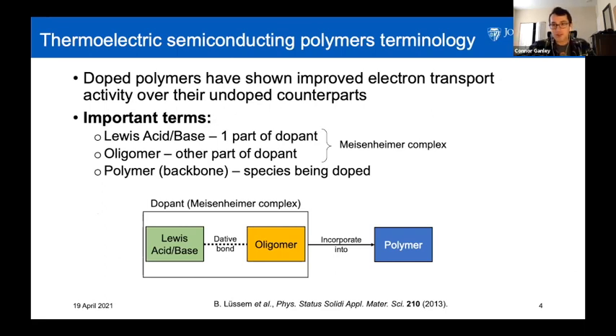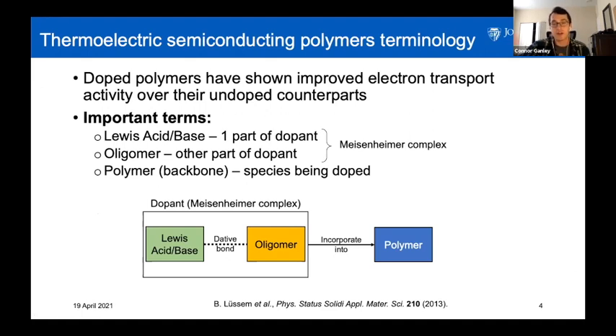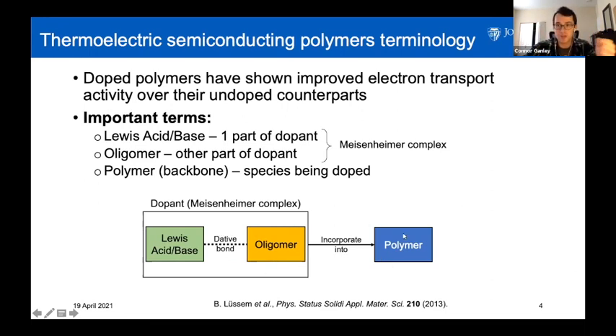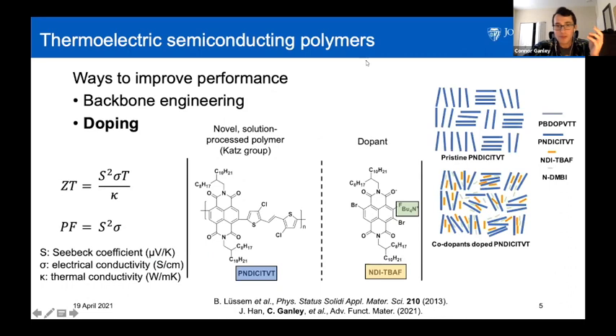With these doped polymers, there are a few terms I need to introduce before I get into the research itself. We form a dopant, which has the technical term of a Meisenheimer complex, which means there are two species — the Lewis base in this case and the oligomer — which have a dative bond. It's not as strong as a covalent or an ionic bond, but it is still a potential energy well where the two species are in fixed positions relative to one another. This is then used to dope a polymer, which improves the electronic activity, thus making it a semiconductor.